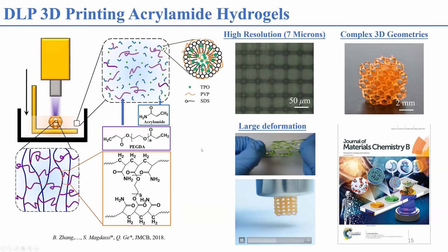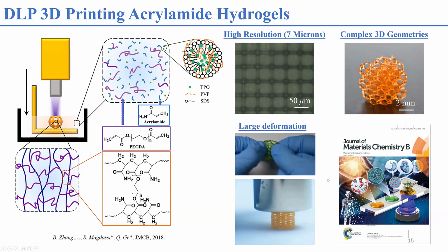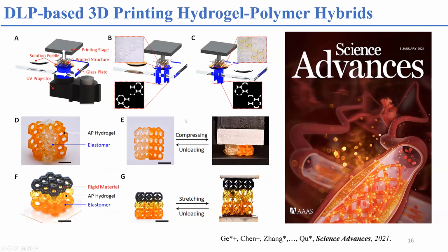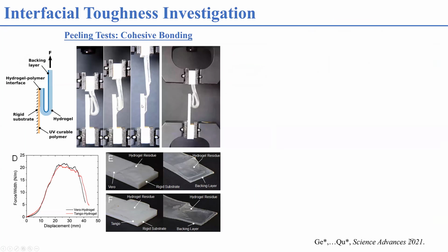And more importantly, we combine this hydrogel with our multi-material printing system. Then we find that our hydrogel can form a very strong bonding with a lot of different materials, such as elastomer or rigid polymer. So therefore, we can print a structure which is half hydrogel, half elastomer, and this structure can sustain large deformation, and there is no debonding in the interface. Also, we can print a rigid polymer and hydrogel, and we stretch. There is no debonding. And we also investigated the interfacial property between the hydrogel and the other polymers, and we find that actually the interface is stronger than the hydrogel itself. Therefore, the hydrogel breaks rather than the interface.